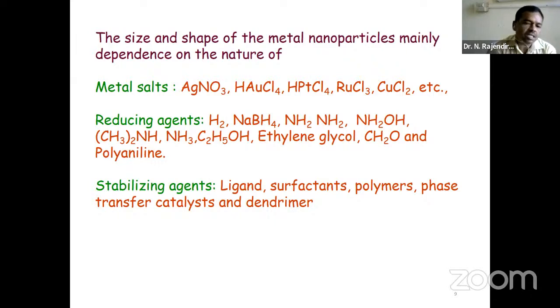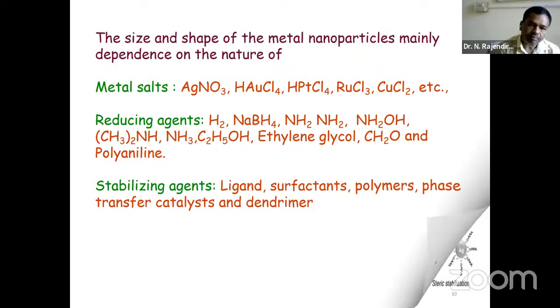And the other one is the stabilizing reagent, where the role of the stabilizing reagent is to control the metal nanoparticles in the desired shape. Because once you reduce the metal salt to the zero oxidation state, what will happen? The particles are continuously growing. So we need to arrest the particles at a smaller size, for which we need to add some stabilizing agent like ligands, surfactants, polymers, phase transfer catalysts, and dendrimers.